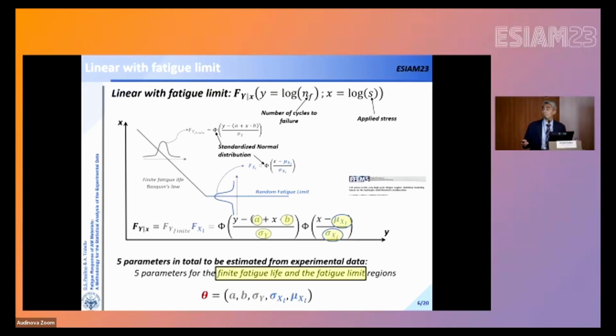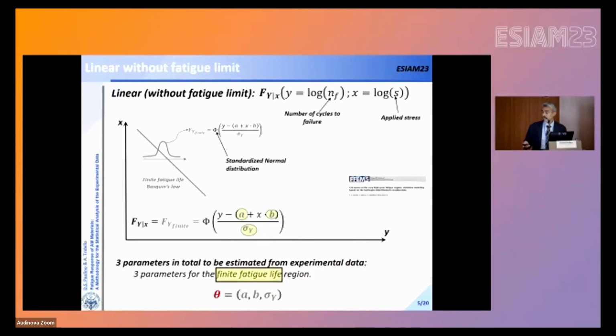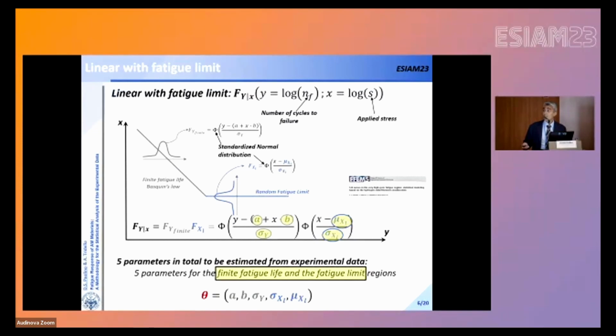Obviously, if we add the fatigue limit region, so we have linear with fatigue limit, the horizontal plateau, then the number of parameters that we have to estimate increases. A, B, and sigma y are related to the finite fatigue life region and are the same as before. But we have to add two more parameters, mu XL and sigma XL, that are the mean and the standard deviation related to the random fatigue limit region.